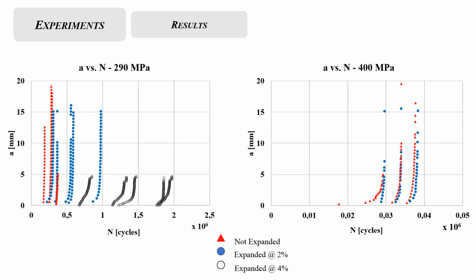It is found that for a cold expansion degree equal to 2%, the fatigue life increases by about 50% to 100%, whereas with cold expansion equal to 4%, an increase of about 200% is found. This is a very important result in the railway sector, in particular for the extension of the fatigue life of rail bolt holes, which is not present in the current literature.